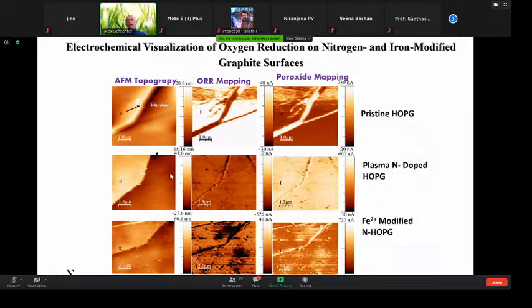Now, we took this surface and exposed it to nitrogen plasma, cold plasma. The reason for wanting to do that is because in the literature the effect of nitrogen dopant on graphitic or sp2 carbon on oxygen reduction is widely described. Namely, if we can embed nitrogen atoms or create defects on the surface, we can enhance the activity of the catalyst. And this is exactly what we did. You see here that there is certain etching of the edge plane, but look what happened. All the surface becomes active. And if you look at the hydrogen peroxide, it follows the same pattern.